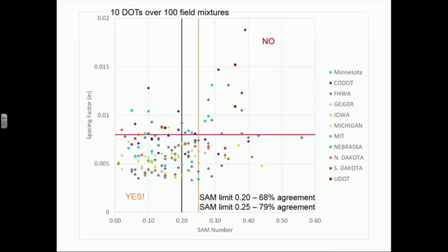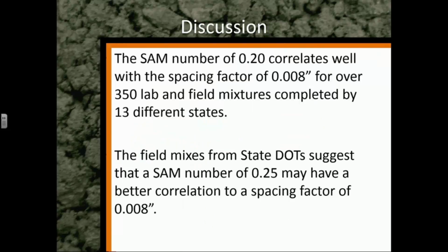And this may be a little bit of that evolution, is that this data is showing that if you moved it over to 0.25, you got a 79% agreement, which is a little bit better. But don't worry, I'll talk more about that coming up. So a SAM number of 0.20 correlated well with a spacing factor of 0.008 for over 350 different lab and field mixtures completed by 13 different states. And the field mixes from state DOT suggest that a SAM number of 0.25 may have a better correlation to a spacing factor of 0.008.